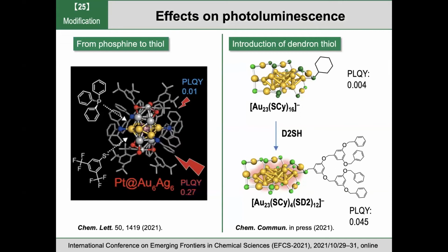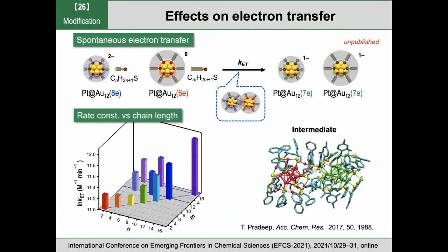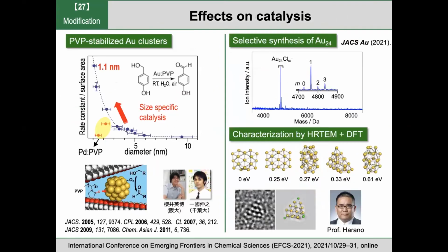Because of the time limitation, let me talk about this. So far, all the surface atoms are protected by organic ligands, so there is no naked area. This means that the catalytic reactivity must be very low, too stable. So in order to use these superatoms for catalytic processes, we have to expose some of the surface for the substrate. And we use a linear polymer to stabilize the clusters, superatoms, like this.